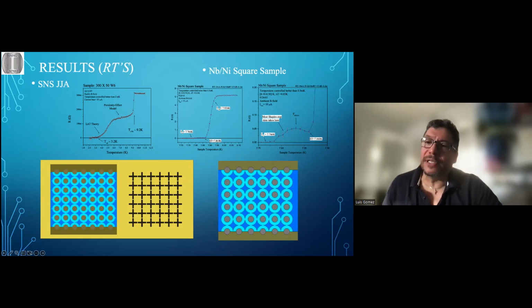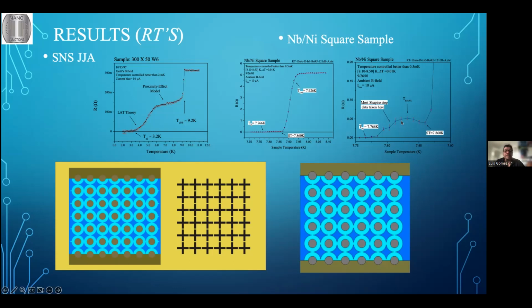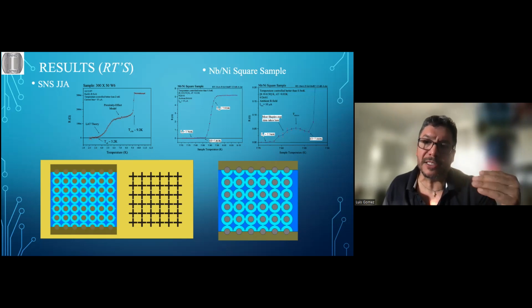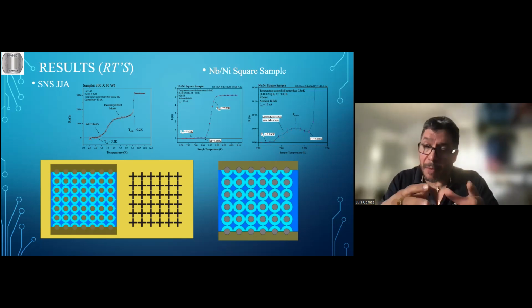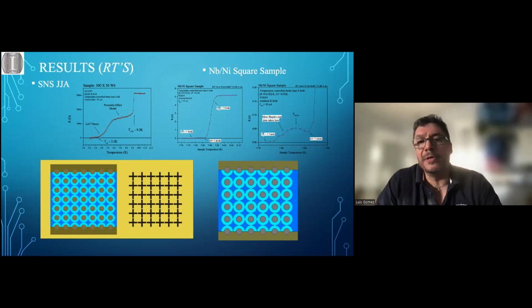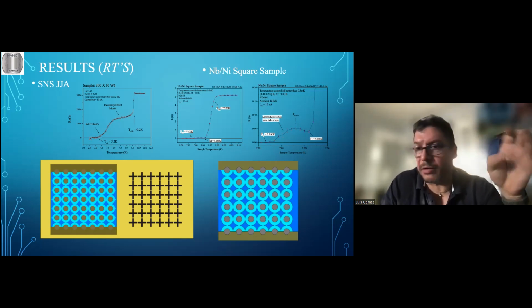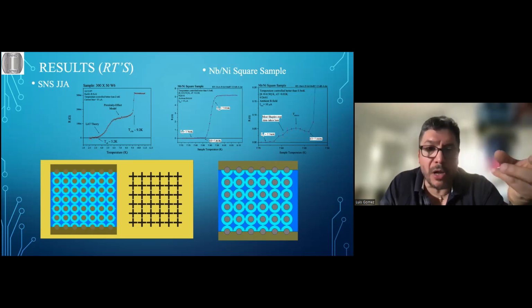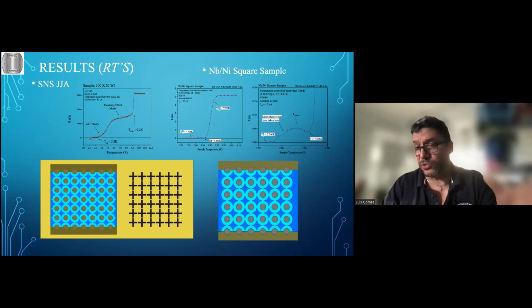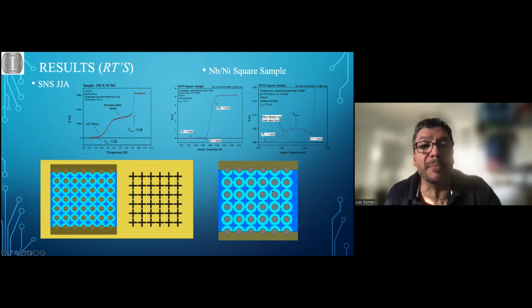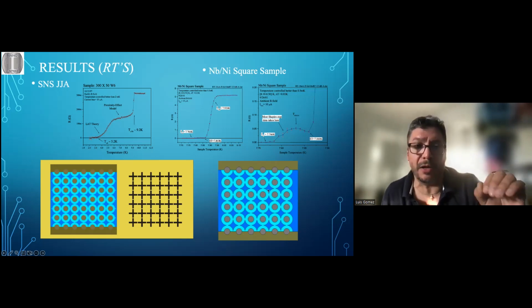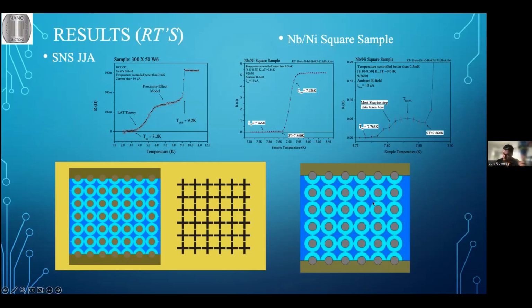So the point is that you have to control the temperature. You go into a region where there is this increase. By placing yourself at this point, you can have this image, that there are certain pockets of non-fully superconducting state. By having a non-fully superconducting state in the regions nearby pockets that are fully superconducting, you basically have the Josephson effect, where non-equilibrium quasi-particles or even Cooper pairs tunnel through other regions that are also fully superconducting. These are represented by these fully dark diamonds in between the circles.